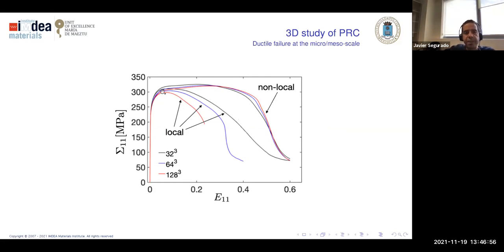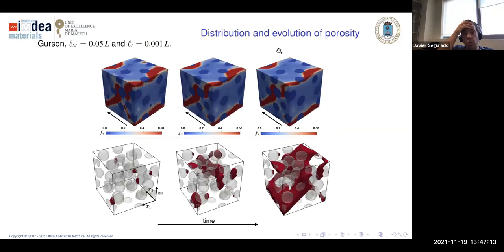On the contrary, whenever we have this gradient enhanced non-local version, all the curves superpose, and we have an energy dissipated that is independent of the discretization of the model. So this thing is good. And what we predict, we can now look at the micro scale and see how damage, in this case porosity, is distributed. What we see is that first, the distribution is independent of the discretization. That's great. So the shape of the bands where damage accumulates is the same from very coarse to very fine discretization. And what we see in this figure is that damage locates in bands that form 45 degrees with the loading direction. That is something that is expected.